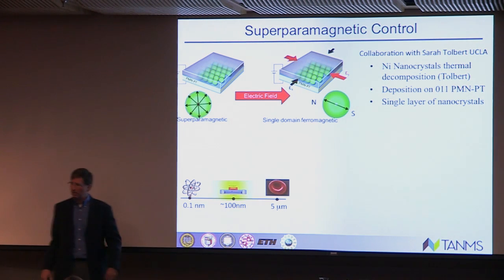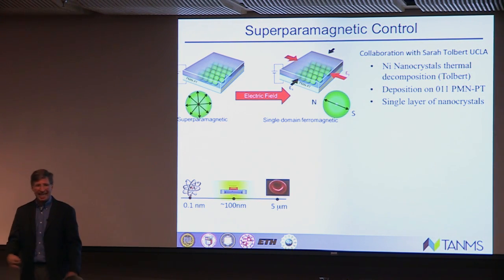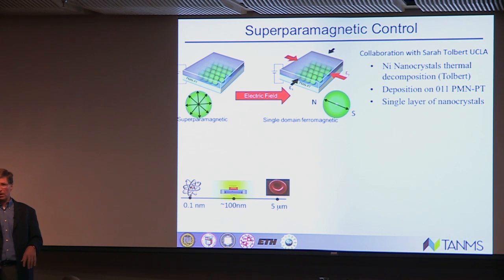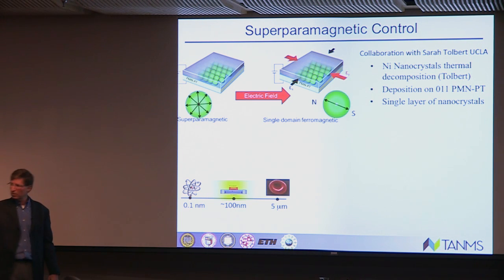So I gave the student the problem. He went off, and after a year, he couldn't make small enough particles. And how small are we? We're no longer at 100 nanometers. We're trying to get down to about 10 nanometers now. So we're approaching the size of an atom. And what we found is he had a hard time fabricating.